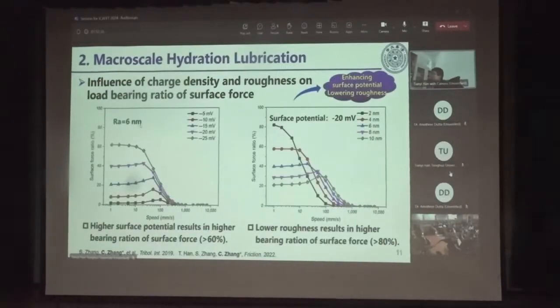First, for the surface with roughness of 6 nanometer, as the surface potential increases, the bearing ratio of the hydration force also increases. And when the surface potential is -25, the hydration effect can bear over 60% of the applied load. And then if we fix the surface potential of -20, the bearing ratio of the hydration force increases with the decrease of the surface roughness, and the maximum is over 80% if the roughness decreased to 2 nanometer.